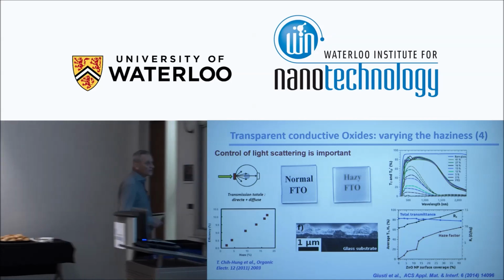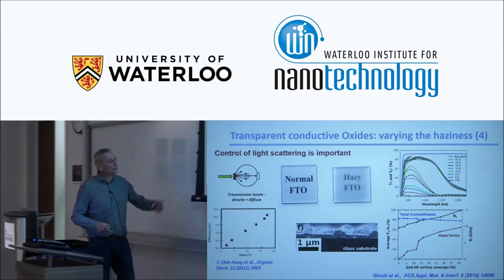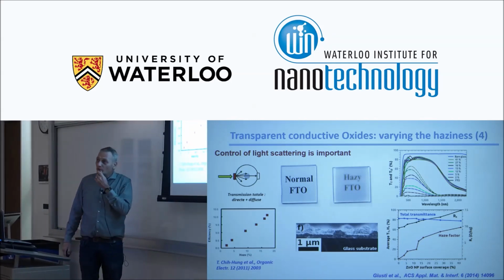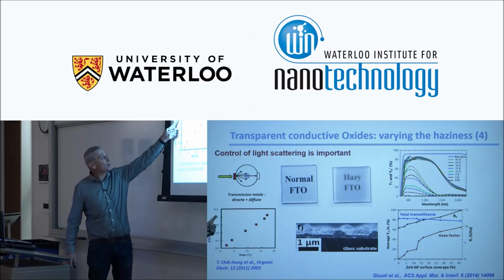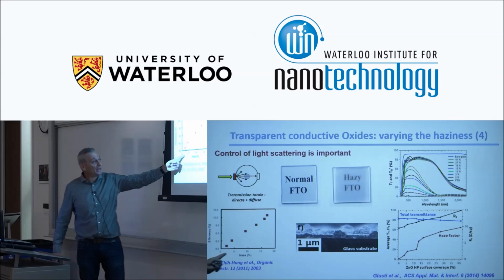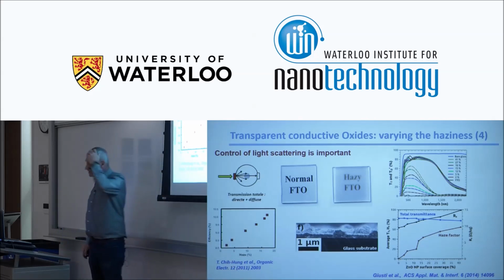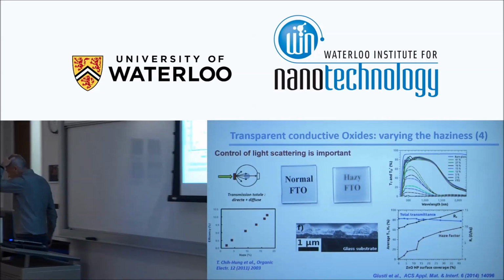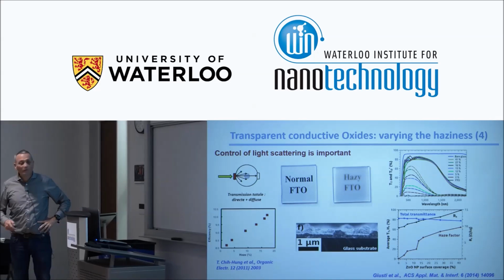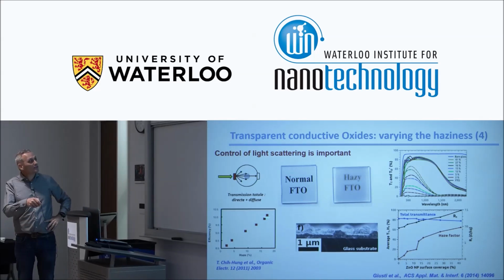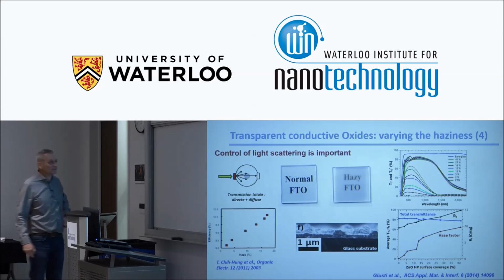And there was an interesting article. There are a few examples in the literature where people, for example, here, studied dye-sensitized solar cells. And they showed that the efficiency of their dye-sensitized solar cell versus the haze was linearly increasing, and that's interesting. There are, I would say, a few teams in the world able to make dye-sensitized solar cells with an efficiency above 10%, and they were able to reach that because they were increasing the haziness.